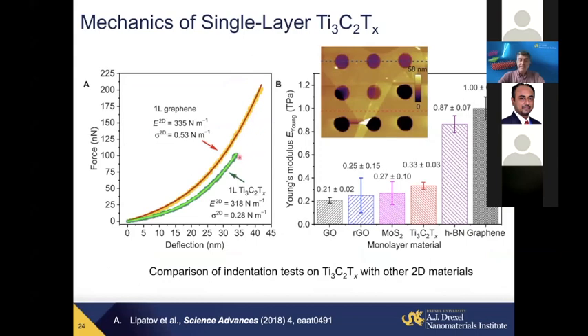While MXene doesn't reach the same properties as graphene, it's still very, very strong. And if you look at its elastic modulus, it's higher than the moduli of any solution-processed material. When we talk about graphene, we're talking about an ideal crystal of graphene, a perfect single crystal, and this one has a high modulus. But if you take graphene from graphite, or reduced graphene oxide from solution processing, mechanically sheared, it will already have lower properties compared to titanium carbide MXene.